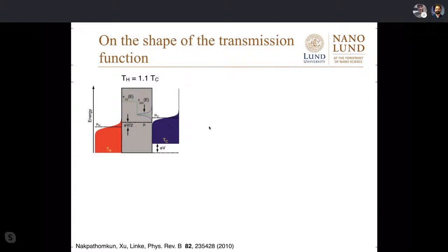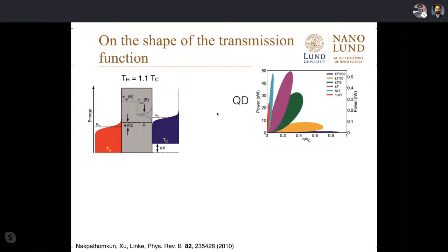Now, the problem with quantum dots is that if you increase the coupling and make your resonance broader so that you get more power out, the performance actually decays very quickly. So here it's a very simple Landauer type model where we estimate the power and efficiency you can get for different widths of this resonance, where we tried to be in this corner down here. We tried to have as narrow a resonance as we can. We even went to slightly higher temperature to decrease our resonance width compared to kT.